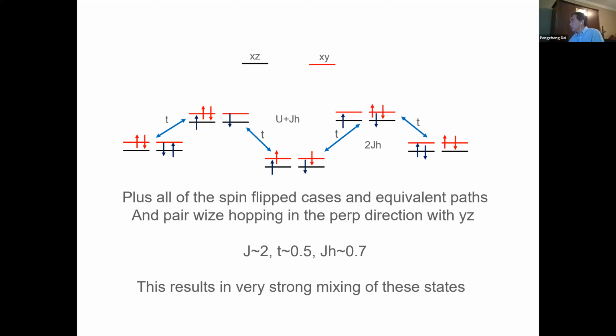So I just want to comment on that because I like this picture very much. It's not only orbital ordering, which you can explain this way, it's also the sensitivity to the external pressure. Take iron selenium, just applying pressure, you can go from 8 Kelvin to 40 Kelvin. You can play the phase diagram with external pressure, and that's very difficult. It's very much different from the cuprates. I think this scenario where the high spin, low spin things play a role is a natural way to explain that. And I like it very much.